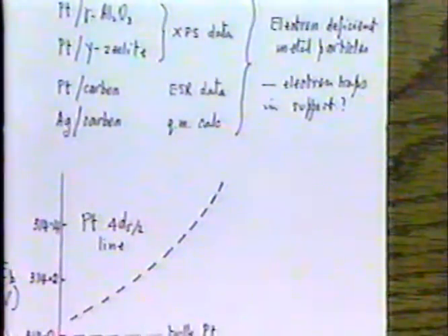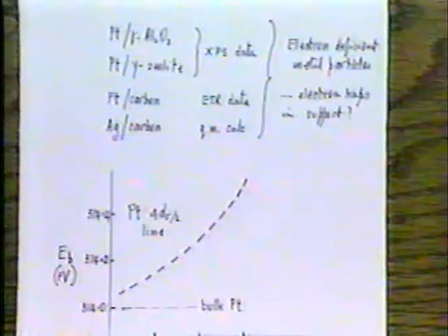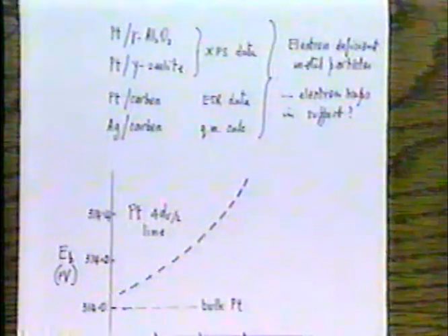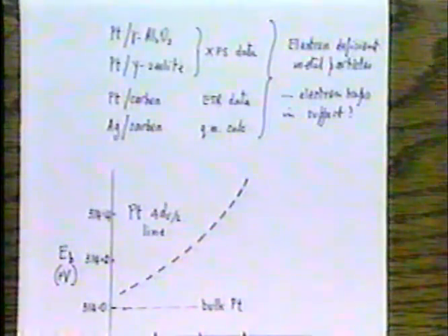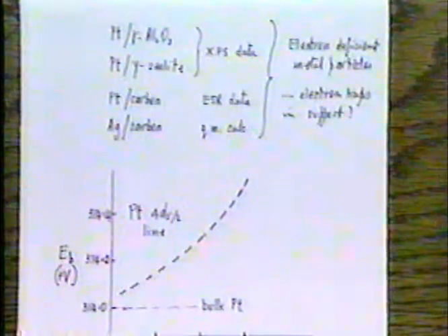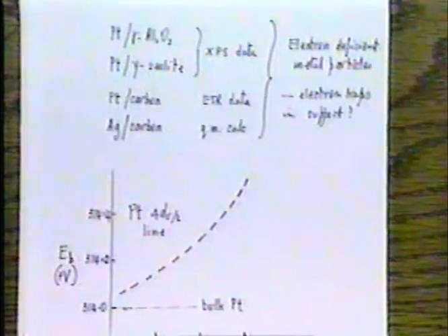There are some similar data for platinum sitting on carbon, in which there's ESR data which shows that the carbon can act as an electron trap. And in that case, what one observed was the ESR signals from electrons in the support, but the electrons came from the platinum. So the platinum is, again, in principle, to some extent electron deficient. And there have been a range of quantum mechanical calculations for various metals, but particularly silver, sitting on various supports. And again, much of this provided some indication that there was a general movement of electrons out of the particle into the support. So, roughly speaking, there is reasonable evidence that very often very small metal particles are electron deficient relative to the particle which exists in principle by itself.